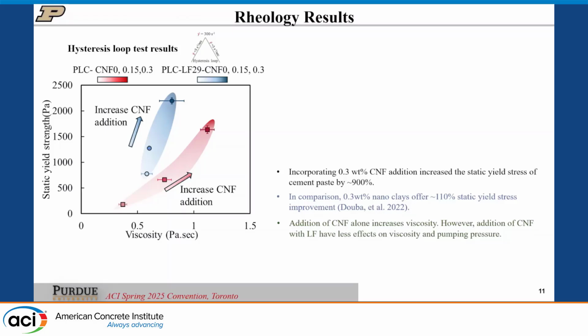But when we add the limestone filler system, even though it increases hydration or causes an acceleration effect, the viscosity is not increasing as rapidly. With that system, because we're changing the hydration kinetics and diluting the cement in a sense - keeping the water to binder ratio constant - we're able to have that increase in static yield stress without a significant increase in viscosity.